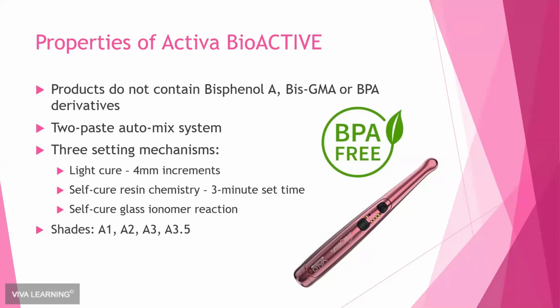So the material can be set through light cure technology in up to 4 millimeter increments. And then it can be self-cured through a glass ionomer reaction that occurs and also the resin chemistry. So the self-cure set time is 3 minutes. The material is available in shades A1, 2, 3, and 3.5, as you can see on your screen.